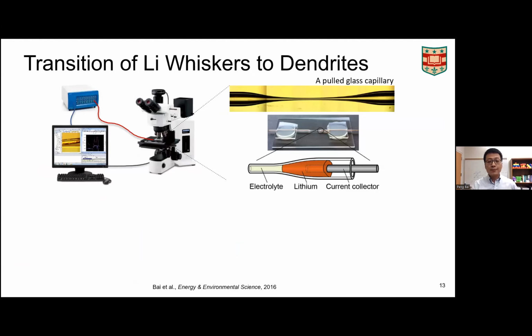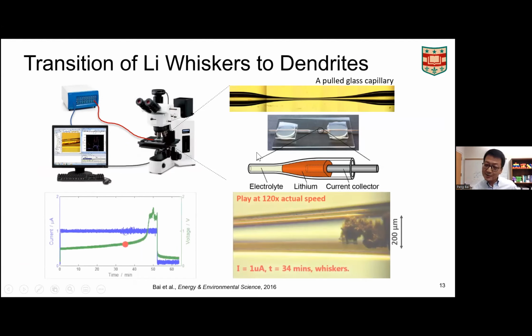And so here, what I did is that I used some very small glass capillary, and I heated the middle part and pulled it. And you can see that then I achieve a thinner part. It is thin enough that under the microscope, everything will be very, very nicely arranged in a single field of view, or in the viewing window, okay? And so then this is what we see.